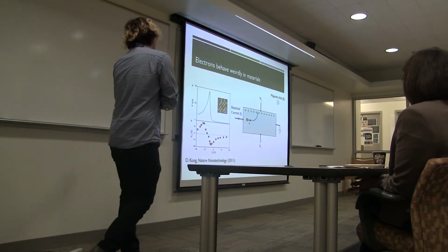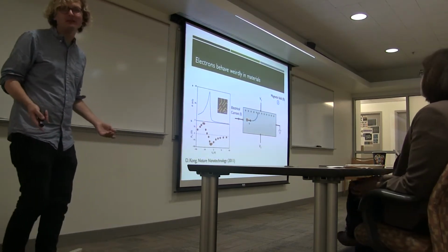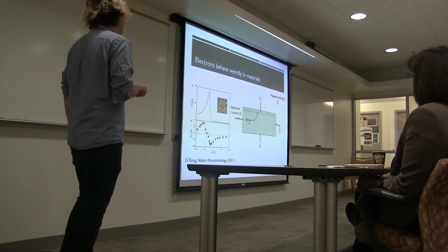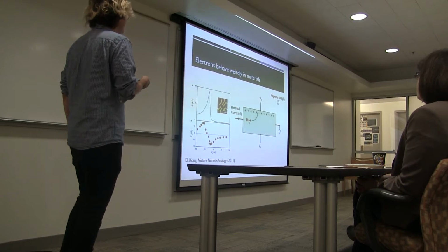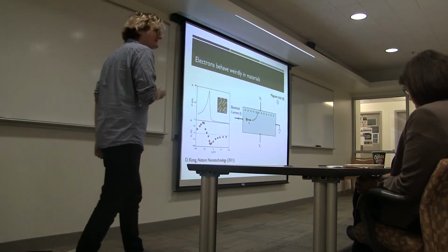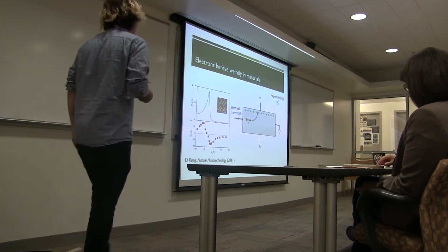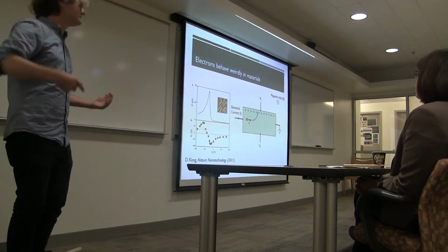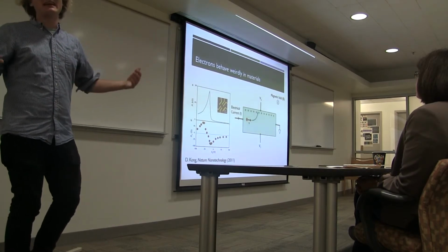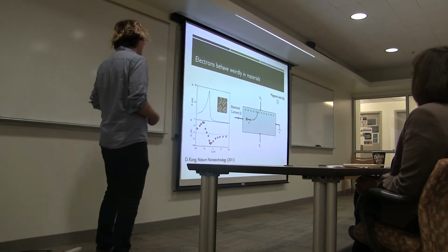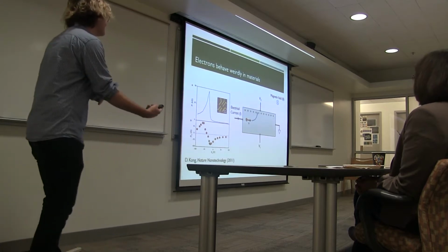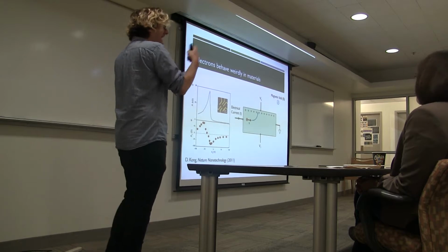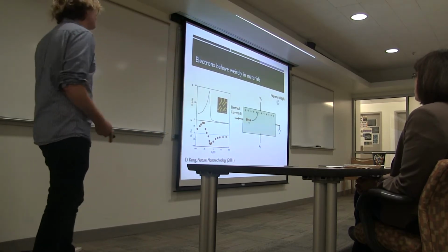And in fact, in the same material, by applying an electric field, you can see a Hall coefficient that goes from positive to negative, indicating that for some electric fields, the charge carriers in this material, bismuth antimony telluride or selenide, act like they have positive charge, and then as you apply an electric field out of the plane, they can act like they have negative charge. And so this is something that's mundane for condensed matter physicists, but it's actually quite weird that you can stick electrons into a system and then they'll behave like a particle that has positive charge.